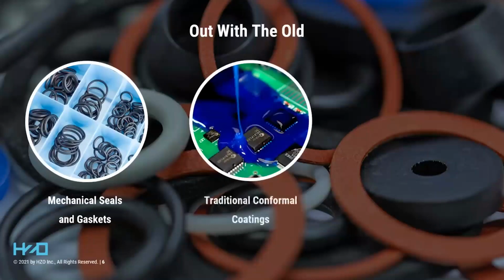Traditional conformal coatings, which we all know, silicones, acrylics, urethanes, things like that, they're generally inexpensive. Though the more features or specific engineered properties you want to have involved, the more cost you're going to have. They can be bulky. They can add significant thickness and weight to a board. Conformality can be inconsistent because the material is wet differently on the surface. You'll get slight air bubbles. You don't get full wetting. You'll get voids around the edges of small components.